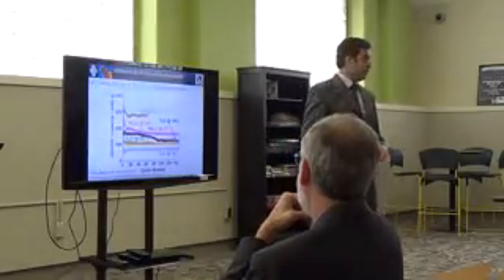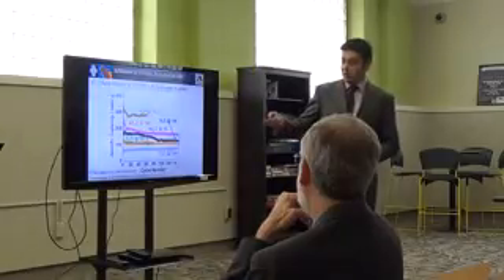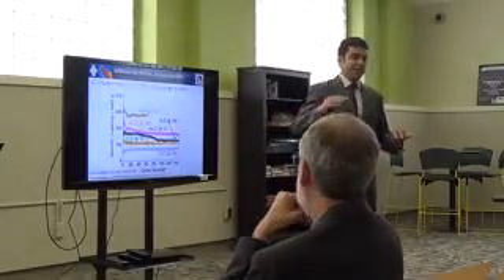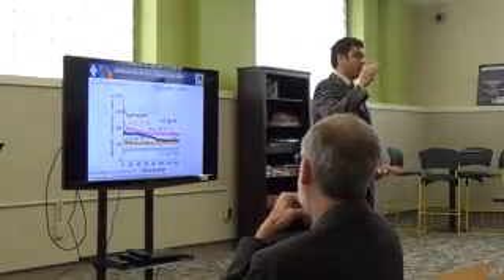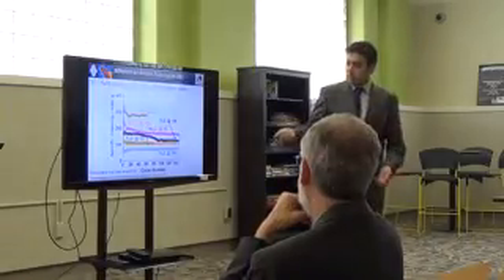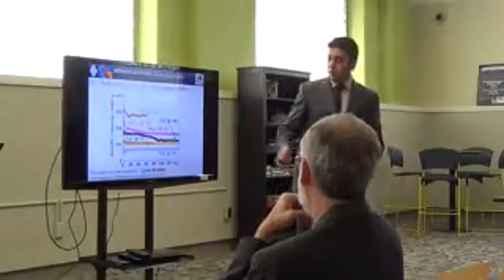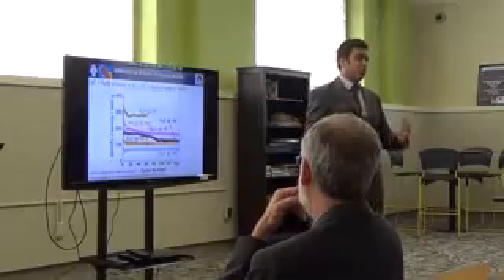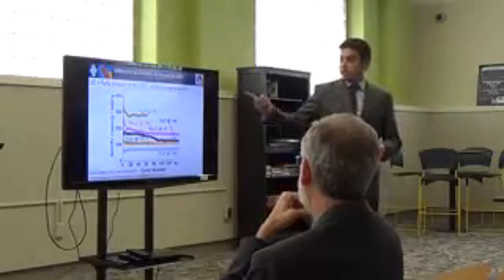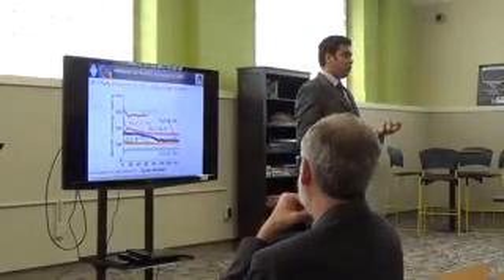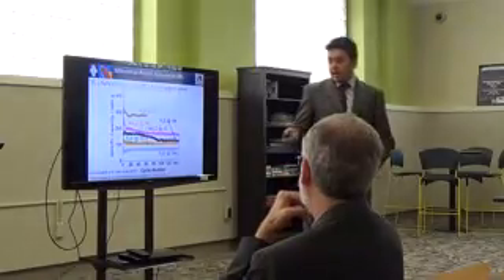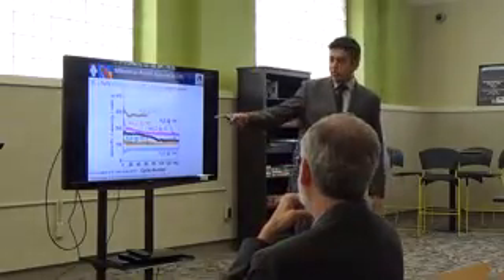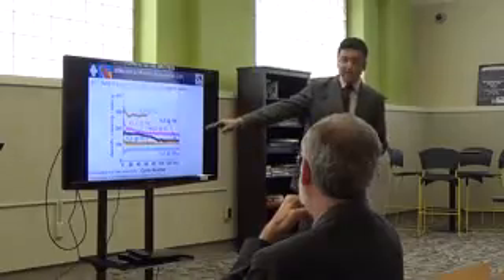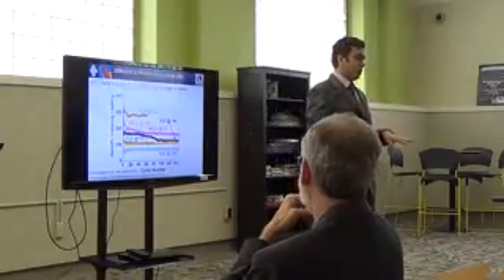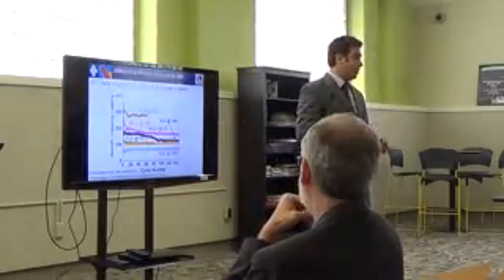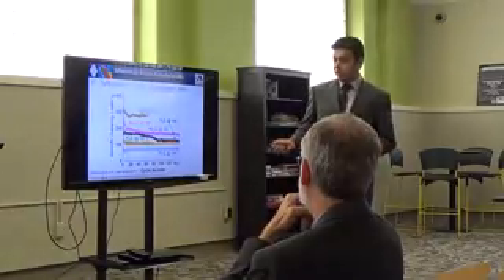We try to test our material in lithium-ion batteries. Here are some results for the capacity. You can consider the capacity as the amount of gasoline you put in your car, for example. Here's the cycling rate: 1C means you fully charge your cell in 1 hour. 10C means you fully charge your cell in 6 minutes. We get capacity a little bit lower than what was reported for graphite, but at high cycling rate we have higher performance than graphite. So we can cycle our material better than graphite at fast rates.